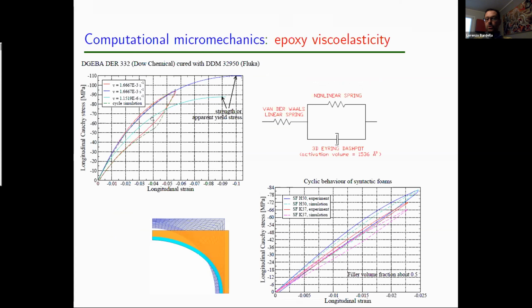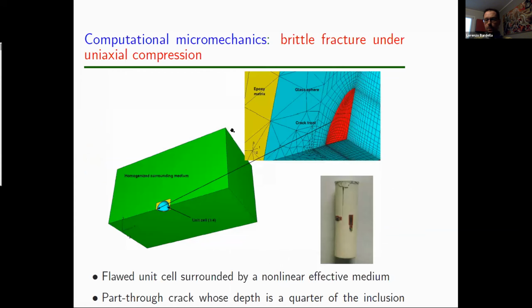About computational micromechanics, that is finite element models, we started by studying the effect of the nonlinear viscoelasticity of the epoxy matrix on the overall behavior. For this purpose, we used a simple unit cell model and we studied the cyclic behavior of various foams by using this constitutive law for the epoxy resins. And then we developed a sort of nonlinear Eshelby-like model, which was used to provide an explanation for the brittle fracture of a specific syntactic foam under uniaxial compression.